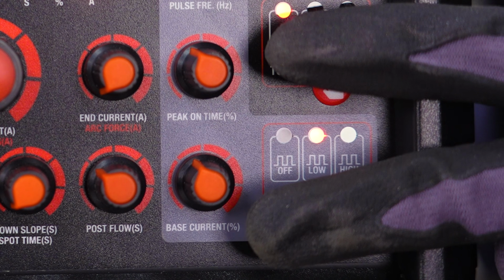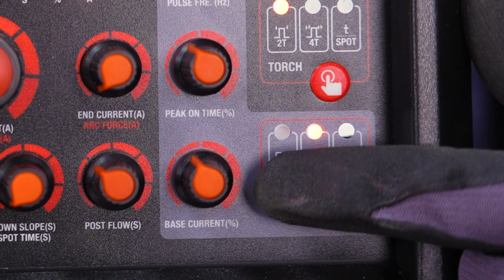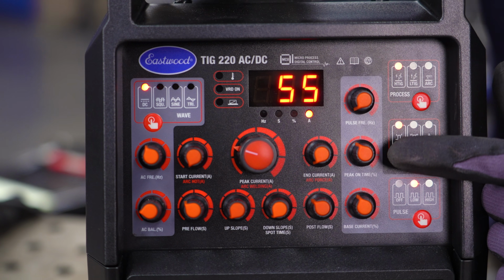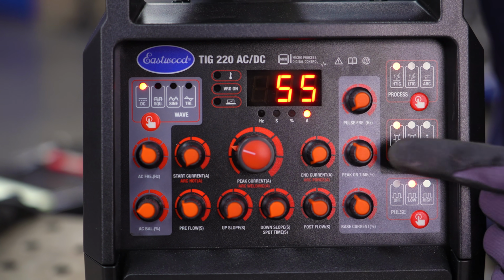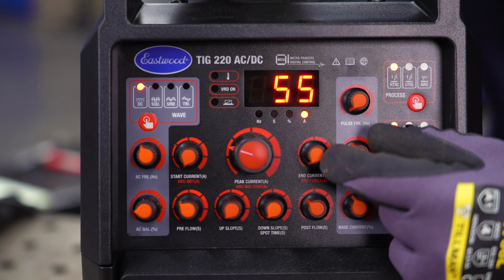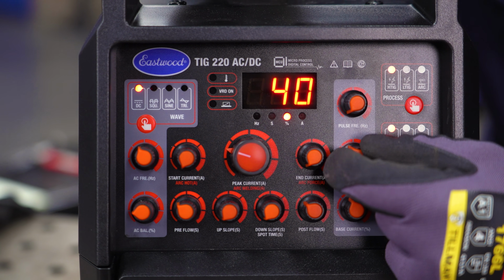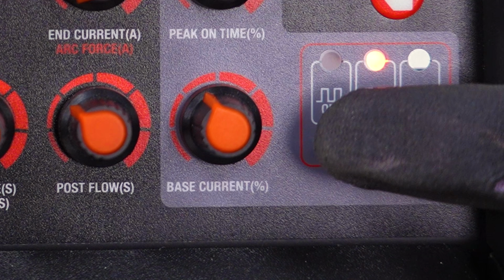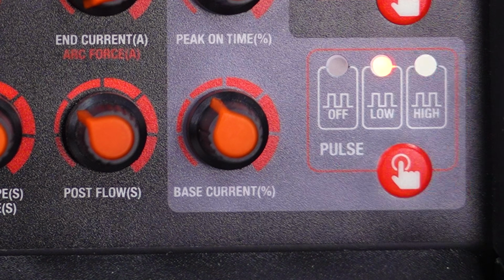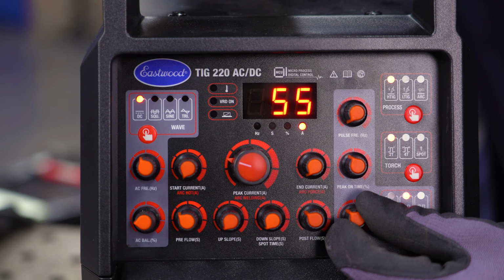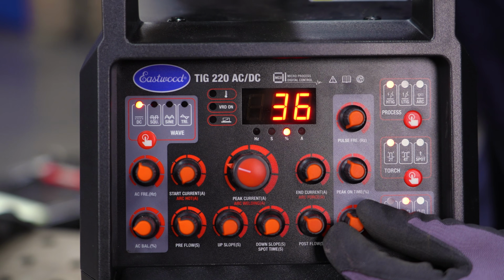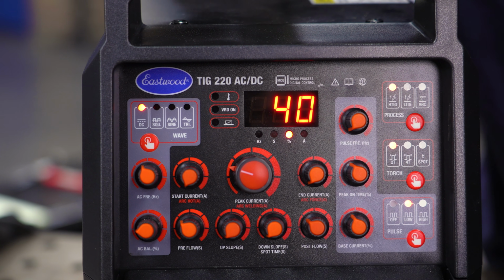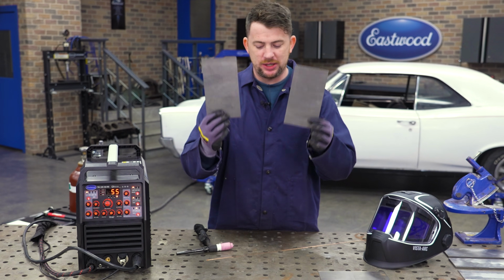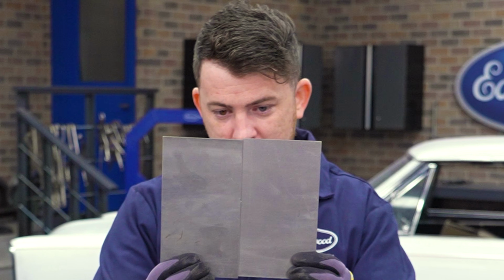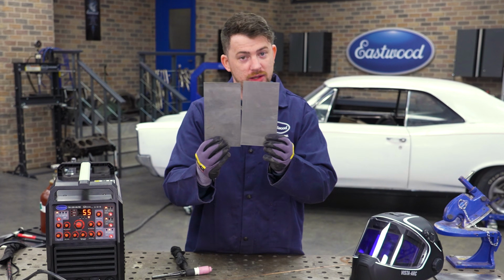These 2 lower knobs are the peak time and the base current. The peak time is how long you're going to be at your peak amperage, which I have already set to 55. I like to start with 40%. And then moving down to the base amperage, I also like to keep that at 40%. I feel like 40% is a good spot to start at, and then you can make adjustments past there as you need. I've cut these 2 pieces of thin sheet metal. What I'm going to do is butt them together. We're going to throw some tacks to lock them down, then we're going to weld them.